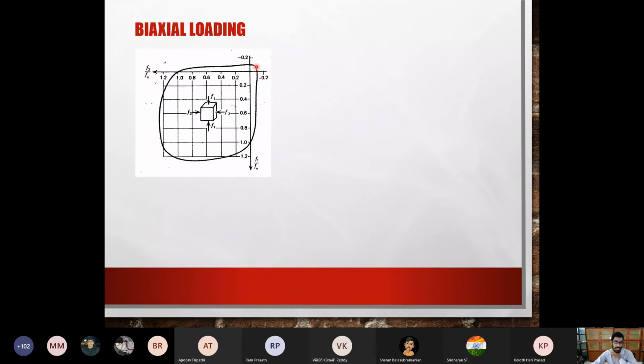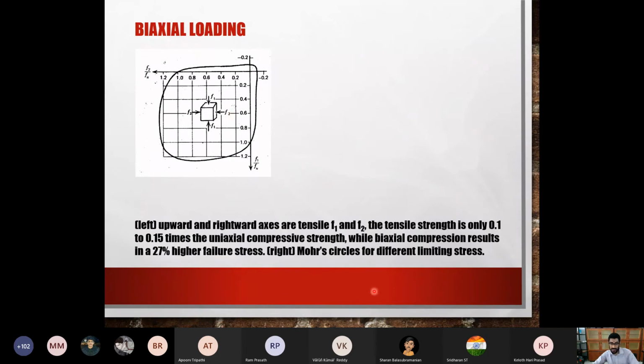However, if one of those directions is tensile, then it becomes really bad. You get less than 20% of the strength which you get by a uniaxial test. For example, if this F2 becomes tensile, then already the side is expanding. You pull it further, it's going to fail much faster. So that is what is happening.